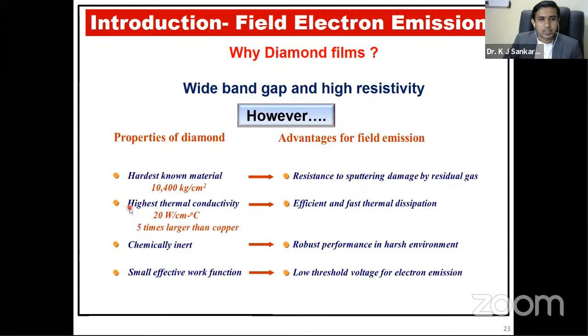The main ones are the high thermal conductivity, chemically inert nature, and small effective work function. These properties of diamond really help us use this material in field electron emission, because with its chemically inert nature, it will be a really robust material in any harsh environment, and a small effective work function helps diamond achieve a low threshold voltage similar to carbon nanotubes or graphene. So we can use these diamond films for field electron emission.